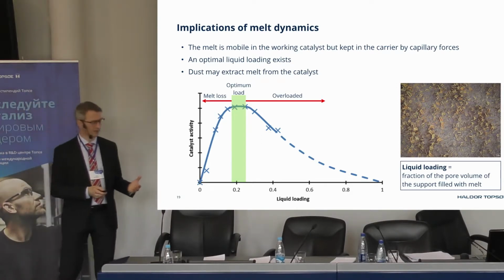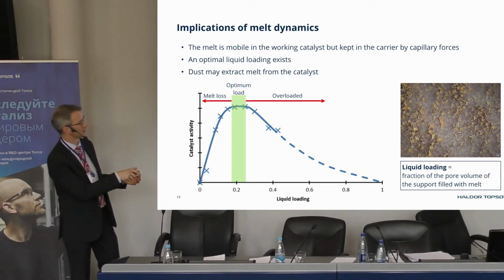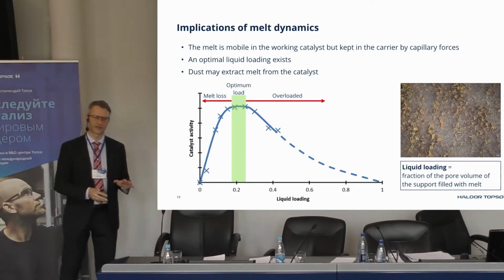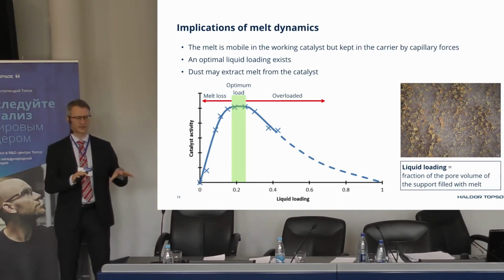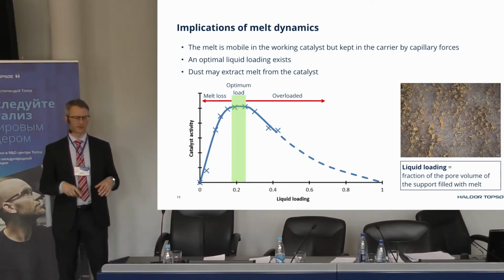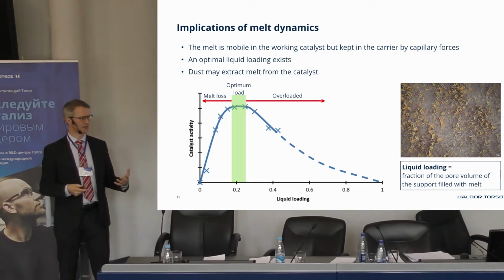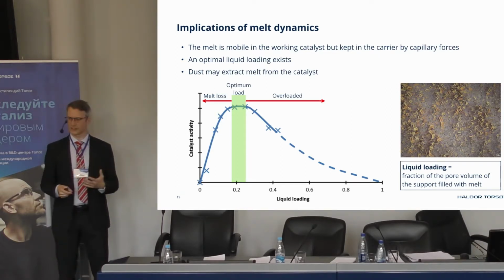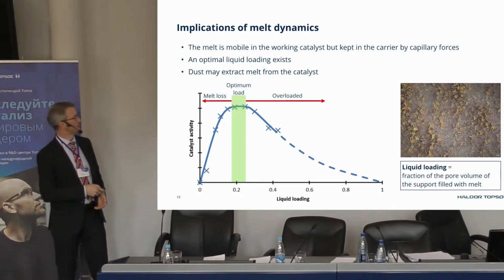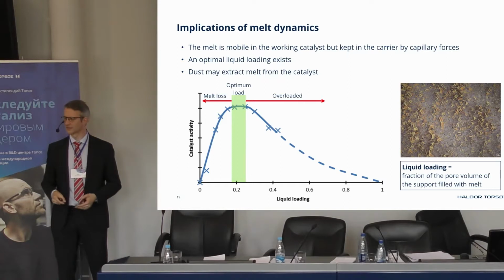So this is overloaded. Another thing that can happen in industry is that dust deposits on the first bed in the converter. It can look like this. When you open the converter, you can see the dust covering the catalyst. Catalyst is quite sticky, and the dust, if it's very fine dust, can extract some of the liquid from the catalyst. And in this way, you will lose the active phase, and in the end, it will deactivate, and you need to replace the catalyst. So this is more on the practical level, but we get the understanding from the in-situ studies on how this works in detail.